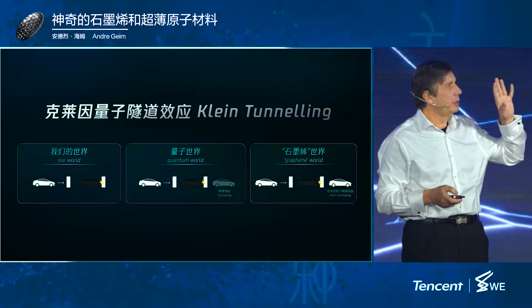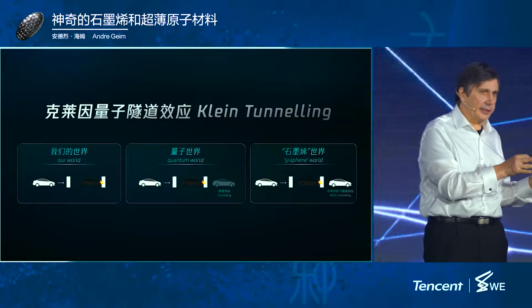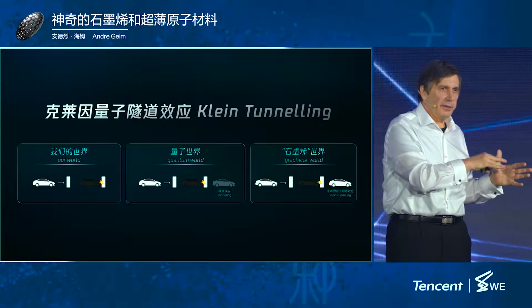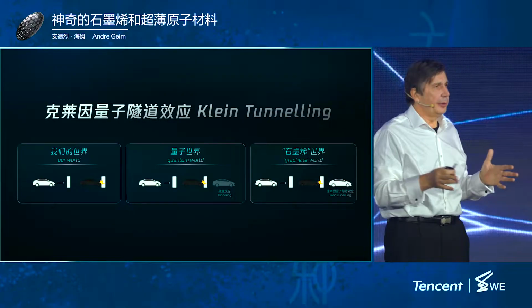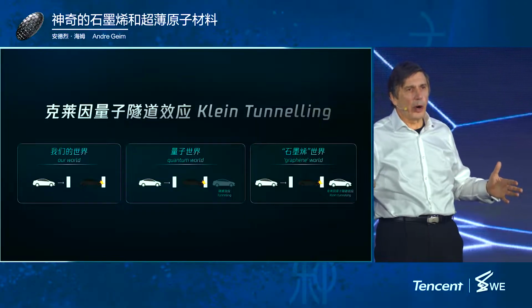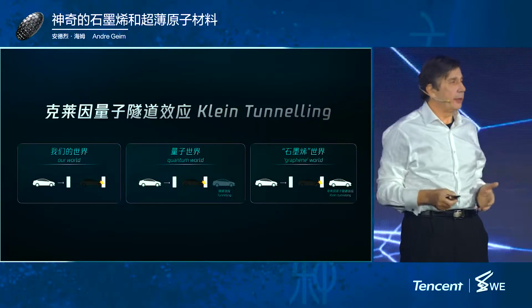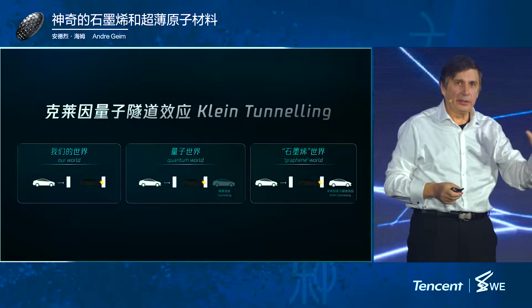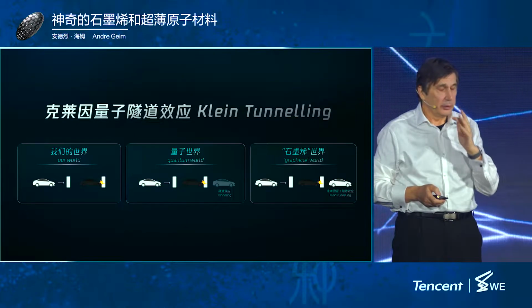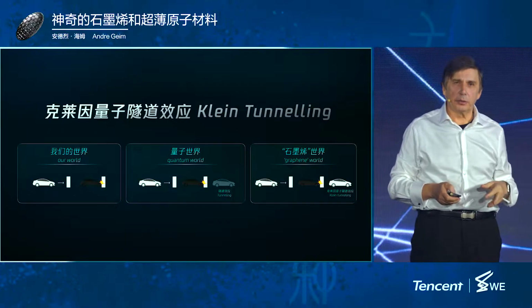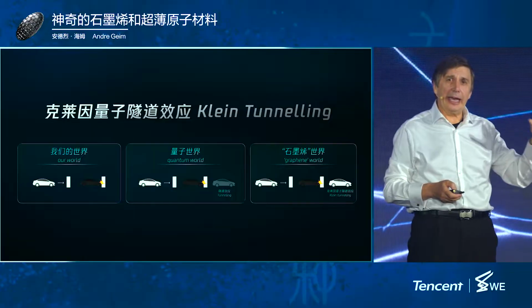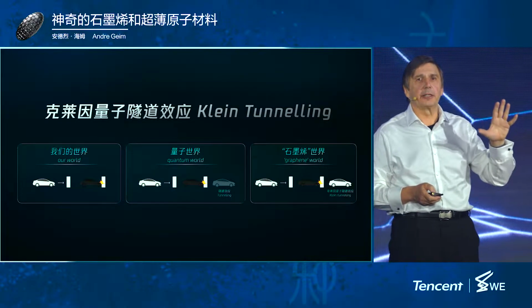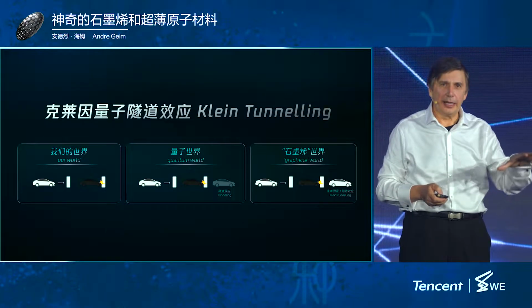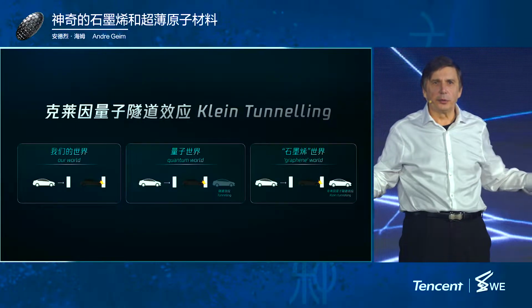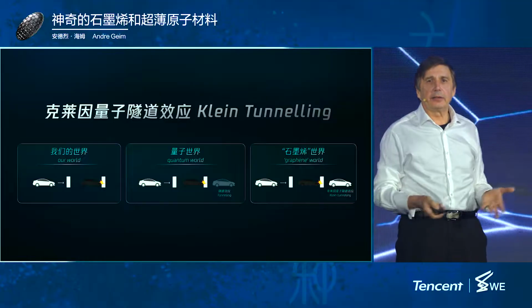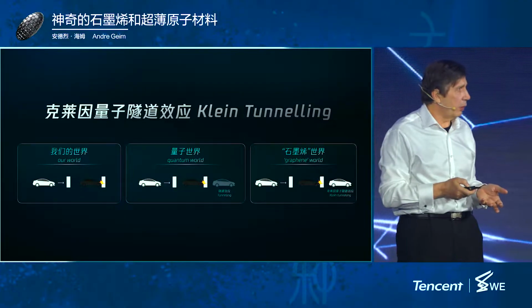In this case, you try to build a barrier for your particles, inside graphene in our case, or in the real world around neutron stars, and however wide or however high the barrier you make, the car living according to the rules of this world will go through without noticing the barrier. Everything goes through. This phenomenon seems weird, but it actually explains why the material is so conductive. You try to localize electrons in graphene, and you can't do that. They just go through very easily, and this is why it's 1,000 times more conductive than copper.